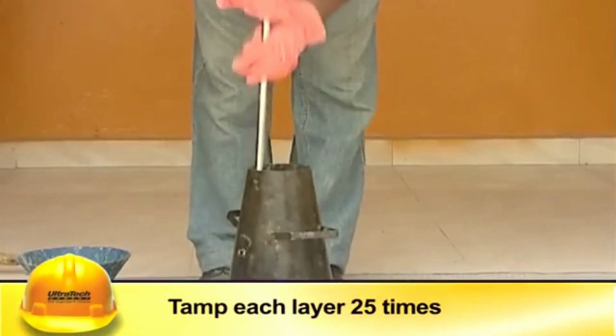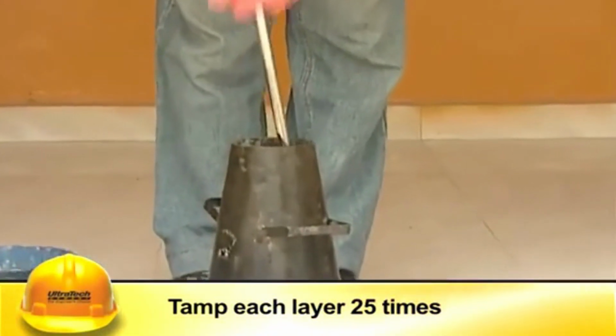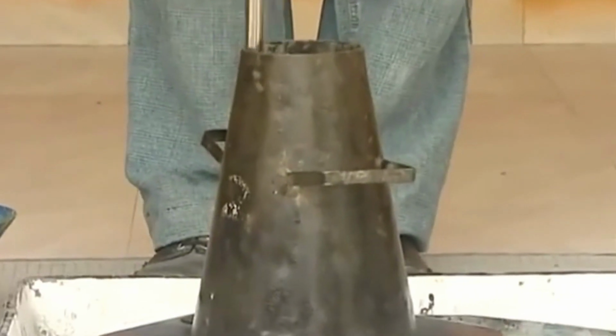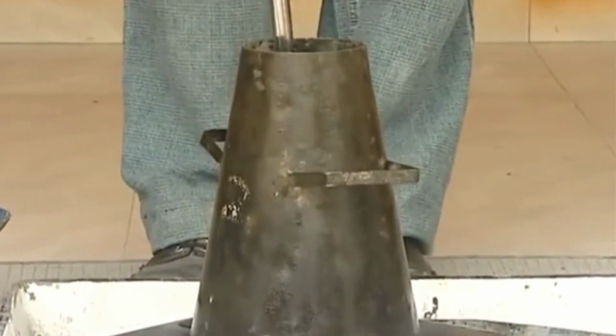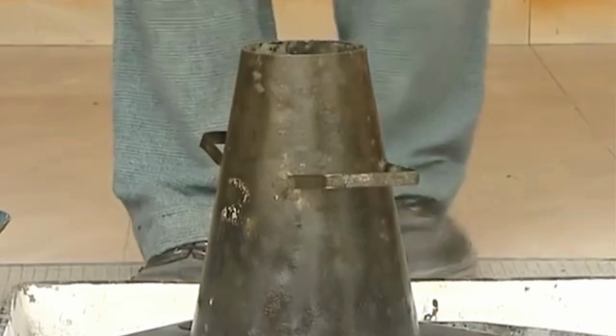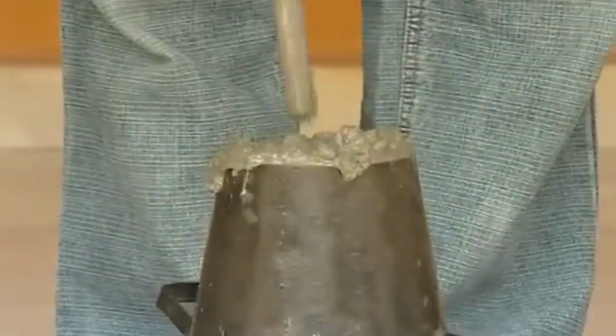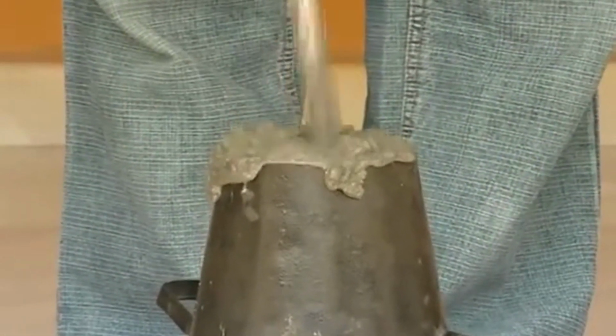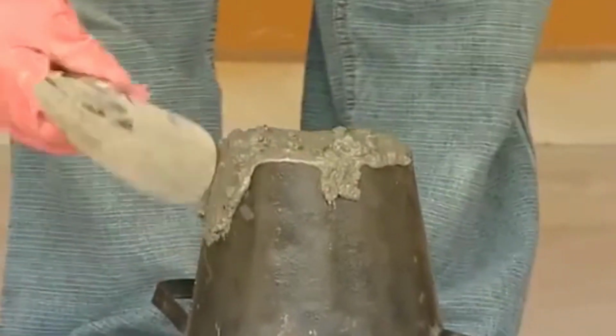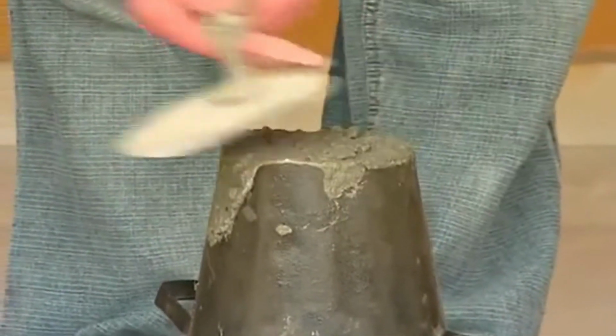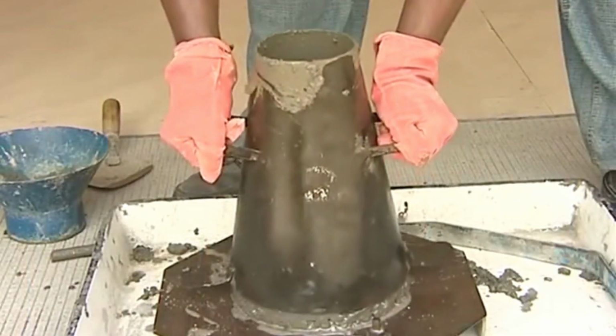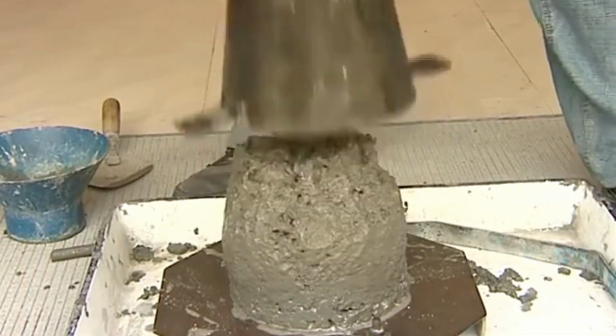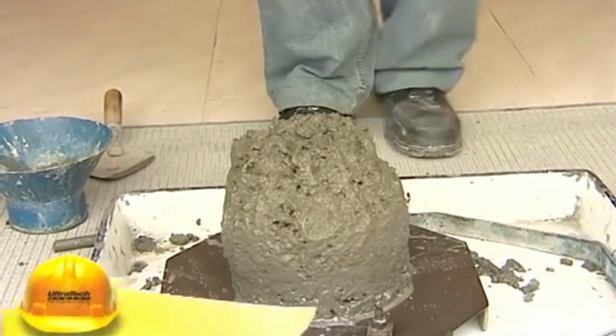Then the mold is slowly pulled vertically and removed from the concrete so as not to disturb the concrete cone. This free concrete deforms and the surface subsides due to the effect of gravity. That subsidence of concrete is the slump of concrete. The height difference between the top of the mold cone and the subsided concrete, in mm, is the slump value of the concrete.